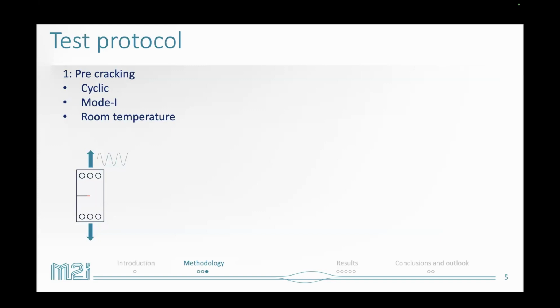So we have the specimen, which has an initial notch made by electrical discharge machining. Using the pre-cracking phase, which is a cyclic loading phase in pure mode 1, I try to get a pre-crack of approximately 1 to 2 millimeters. And these tests are done at room temperature.